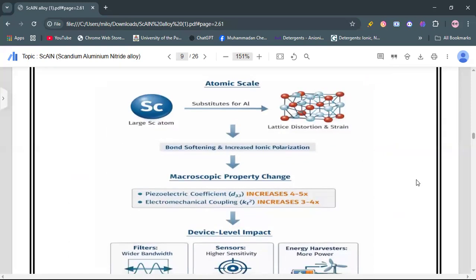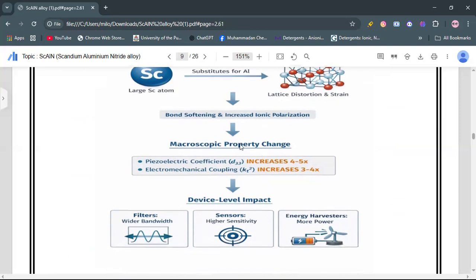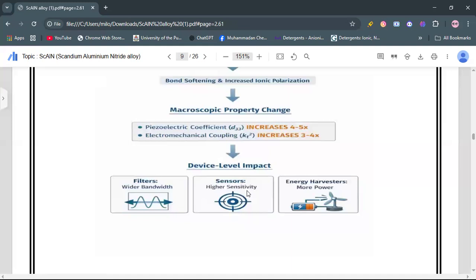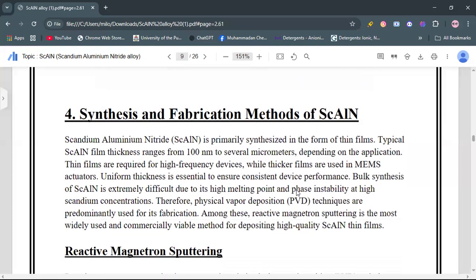Here's a diagram which shows that when the scandium atom is introduced into the aluminum nitride lattice, the result is bond softening and increased ionic polarization, which affect the macroscopic properties and increase the piezoelectric coefficient up to 4 to 5 times, and electromechanical coupling increases 3 to 4 times, which affects device-level impact. For example, wider bandwidth, increased sensitivity of sensors, and more power from energy harvesters.